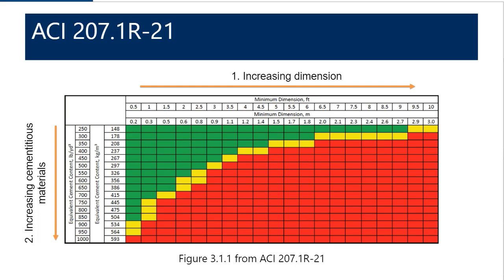And oftentimes it is thermal cracks. It could be plastic shrinkage cracking as well, but it could also be thermal cracks. The interesting thing is that you can actually get thermal cracks, and it depends on the mixture, and it depends on the heat profile of a given mixture. But you can get thermal cracks when the temperature differentials are as little as 15 degrees Fahrenheit.